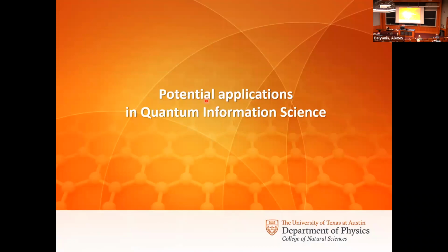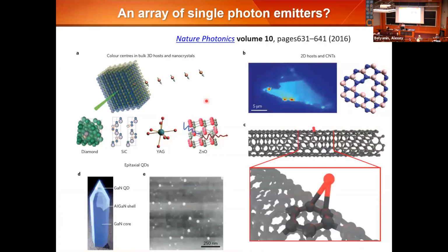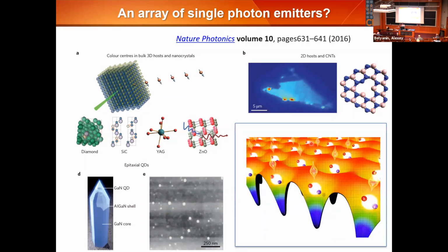I do want to speculate what else we can do in quantum information science. So one thing is single photon emitters. There are a lot of solid state single photon emitters, but they're mostly based on defects in a high gap material or these self-assembled quantum dots. As you can see, here's a quantum dot. They're randomly spaced with changing size. You can also modify a carbon nanotube, but none of them has well-defined directions, and they have different energies. But with the Moiré supercell, I potentially have a regular array of single photon emitters. That's one area where it can make an impact.